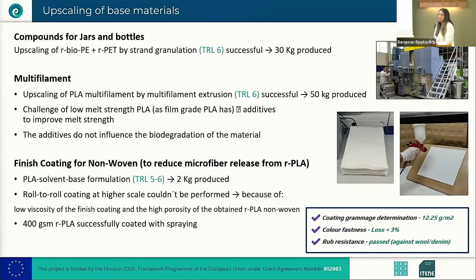For these solutions, it's the same story. We have different production steps that we have to go through to finally make a packaging. Therefore, first, we have to make compounds for the bottles as well as for the jars, and we successfully used recycled bio-based polyethylene and recycled polyester. We did some additivation, of course, that is always needed to have a successful material, and we produced around 30 kilograms of these compounds.